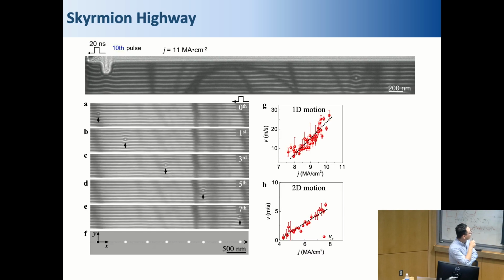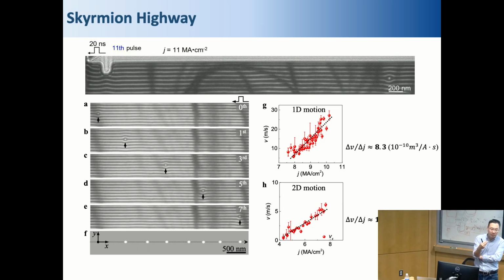And we can analyze the velocity. The velocity is still a linear function of the current injected. But if you compare the slope of the Vj curve, what I showed in the previous slide, the free motion of skyrmion in 2D, the slope is about 1, up to 10 to the minus 10 or whatever unit. But for this one, the slope is 8.3. So that means given the same structure, the same material, if you have the skyrmion confined in the transverse direction, the velocity would be almost 1 order of magnitude higher than free motion of skyrmion.